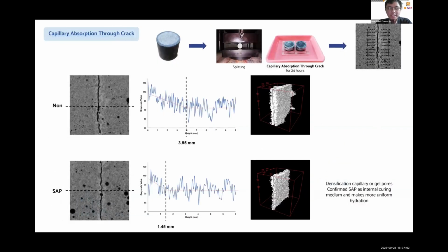To observe the durability, capillary absorption through cracks was tested. The specimen is split and capillary suction is applied using potassium iodide as tracer for 24 hours. Therefore, we can observe the penetration of the tracer. The non-SAP specimen penetrated almost 4 mm and the SAP specimen just around 1.5 mm. This densification of capillary or gel pores confirms SAP as an internal curing medium and makes hydration more uniform.